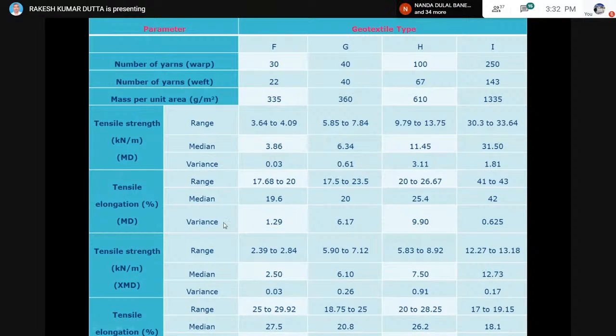Now in this table, I am showing you four different types of geotextile: type F, type G, type H, type I. If you see the number of yarns in the warp direction or the machine direction, they are 30 for the first one, 40 for the second, 100 for the third, and 250 for the fourth one. Number of yarns in the weft direction, that is the cross machine direction, 22, 40, 67, and 143. And mass per unit area, 335, 360, 610, and 1335.